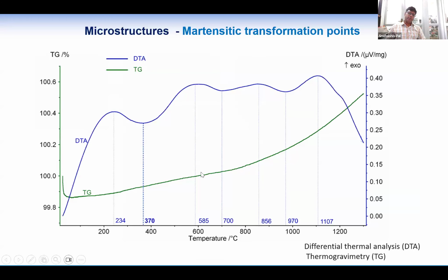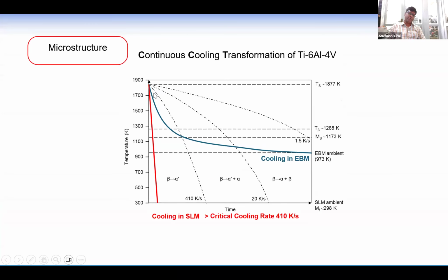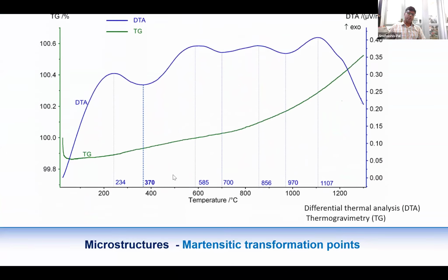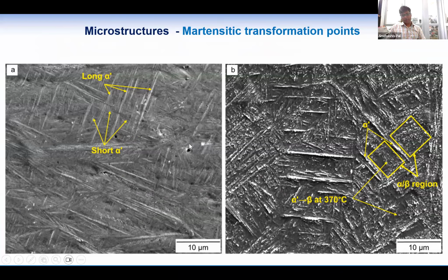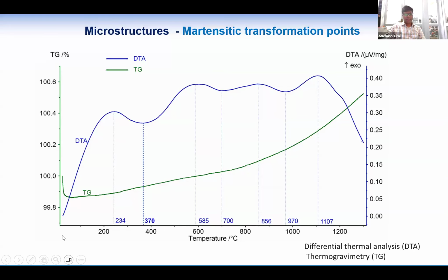However, there are a lot of other microstructure possibilities. Let's say if we change the temperature and something like this, we can change the microstructure. We can see how it's actually formed. This is the DTA result. Let's say we heated up the material after manufacturing the part, and we got several up and down, exothermic and endothermic reactions in the material. Therefore, the martensitic formation started even from 370 degrees centigrade during the last heat cycles.